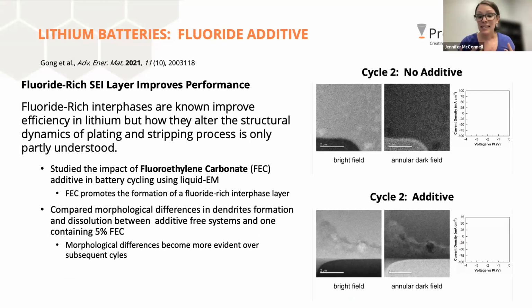And in this last example for batteries, they're looking at enriching the SEI layer. The understanding from bulk ex situ testing is that if you enrich the SEI layer with fluorine, and here they're using a fluoroethylene carbonate, the battery life is extended. The battery seems to be more efficient.